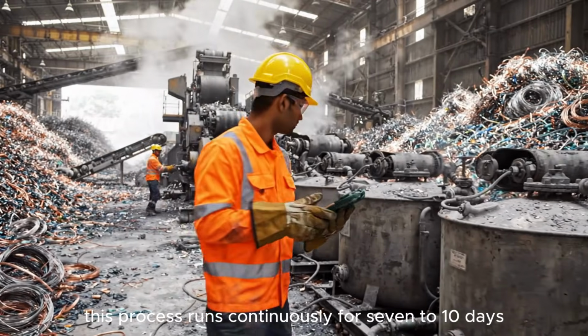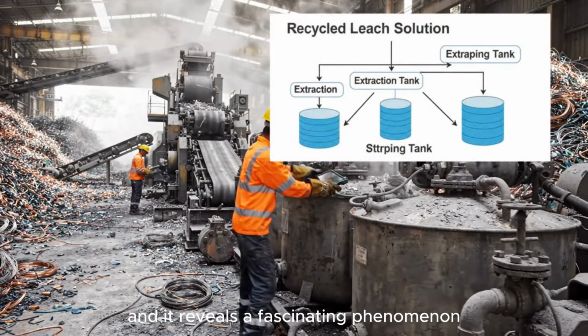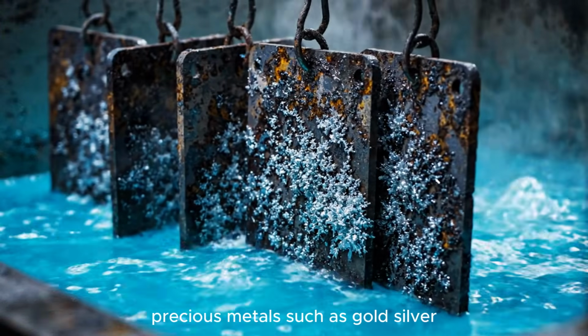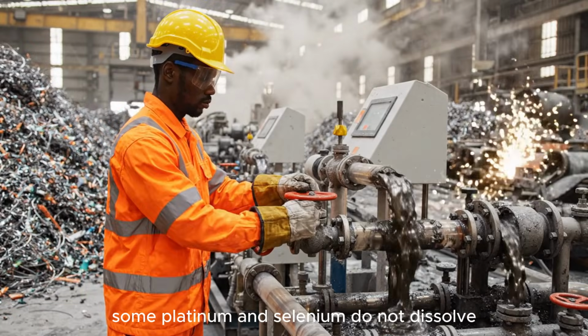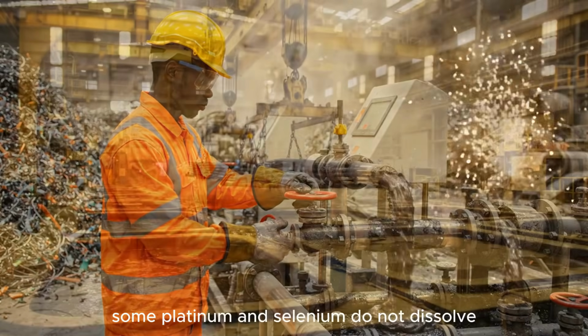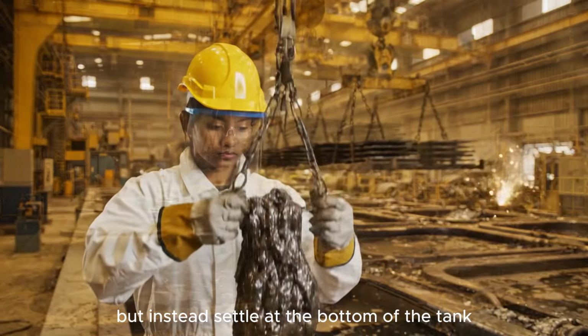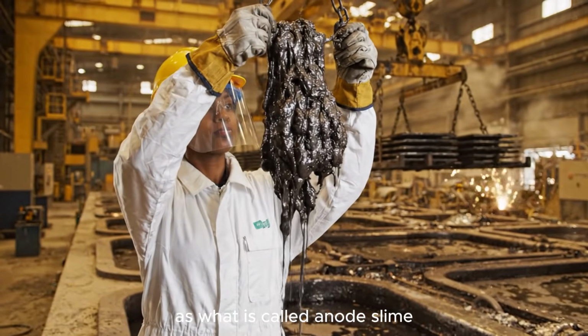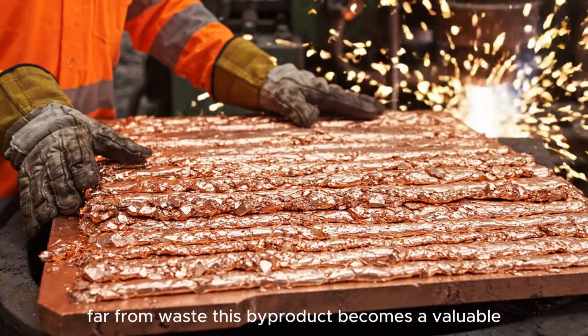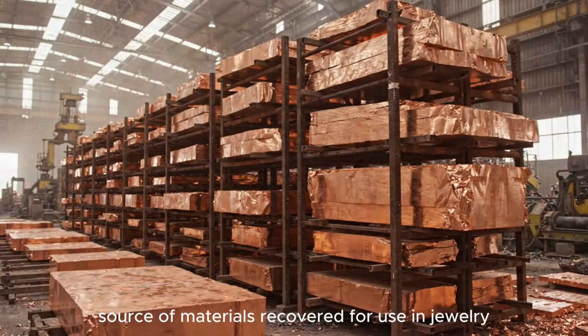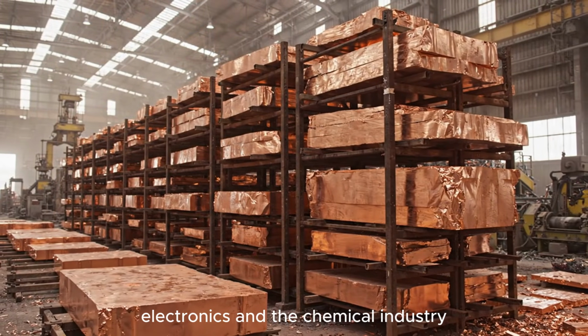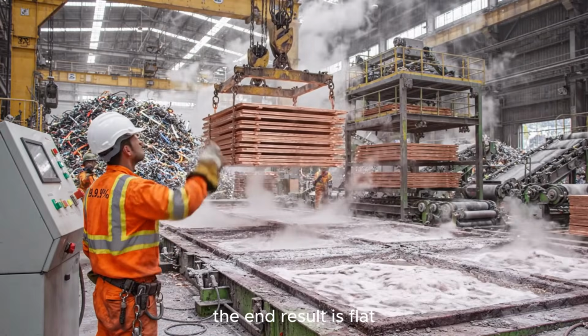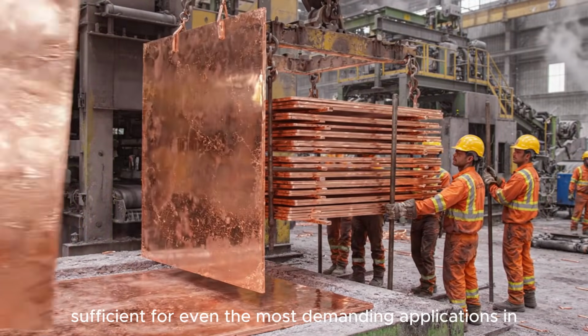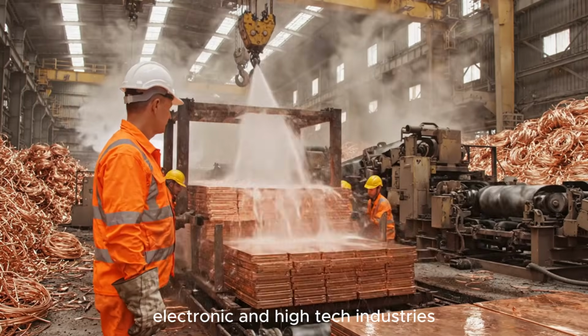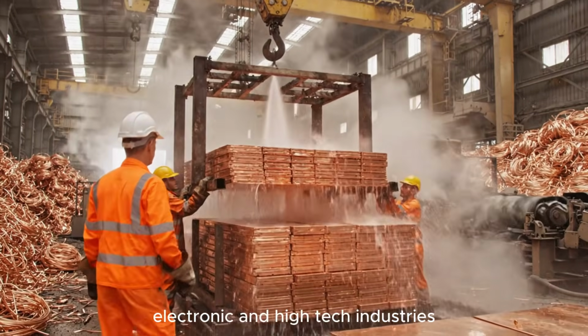This process runs continuously for 7 to 10 days, and it reveals a fascinating phenomenon. Precious metals such as gold, silver, platinum, and selenium do not dissolve but instead settle at the bottom of the tank as what is called anode slime. Far from waste, this byproduct becomes a valuable source of materials recovered for use in jewelry, electronics, and the chemical industry. The end result is flat, thin cathode sheets of copper with a purity of 99.99%, sufficient for even the most demanding applications in electronic and high-tech industries.